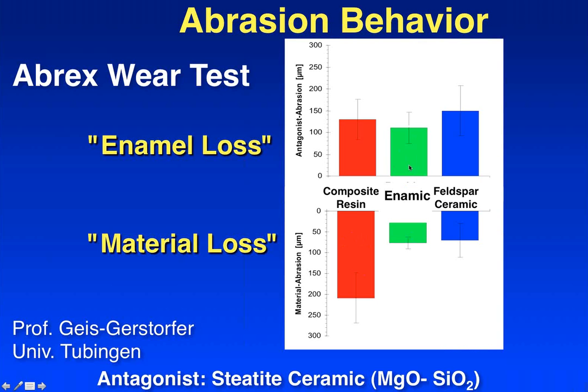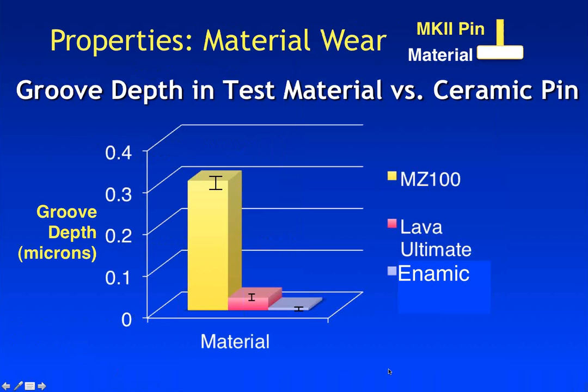So indeed, in this test, it shows that we are in between the worlds of ceramic and composite resin. We have a material that is wear kind, it doesn't destroy the opposing dentition, and we have a material that's very stable. It doesn't lose thickness during wear testing or theoretically in the mouth. And so we are in between both worlds of materials.